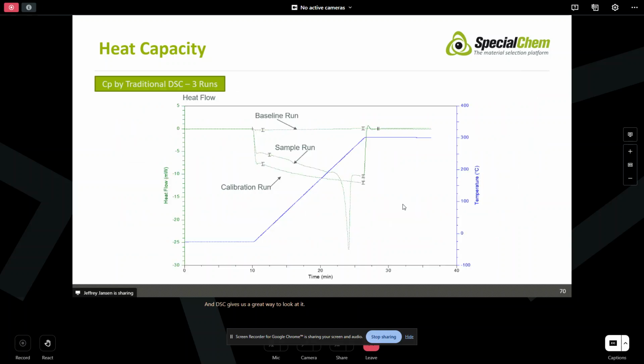So there's two basically different ways to do that. Traditionally, in older pieces of equipment, you can get that heat capacity by doing three separate runs. You run a baseline run, you run a sample run, as well as a calibration run, and you can then get the heat capacity of the material through that process as a function of temperature by comparing those three.